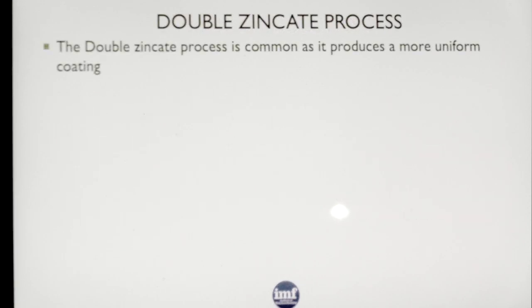Most zincate processes, you can do it once. You can take your aluminium, you etch it, you rinse it, you put it into your zincate process, you leave it for about 1 minute, you take it out, you rinse it. You can plate that, and you can get good adhesion. But if you go to a double zincate process where you zincate it, you strip the zincate back off again, and then you zincate it again, but half the time of what you did in the first one, your adhesion almost doubles. So a double zincate process is very, very important.